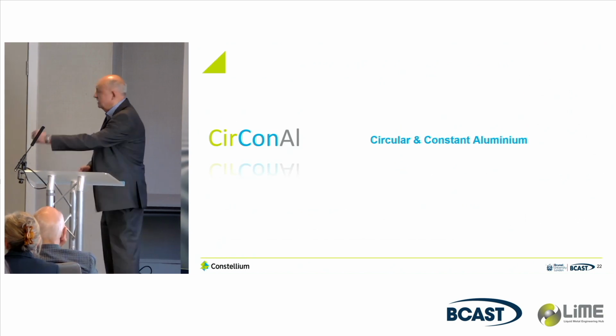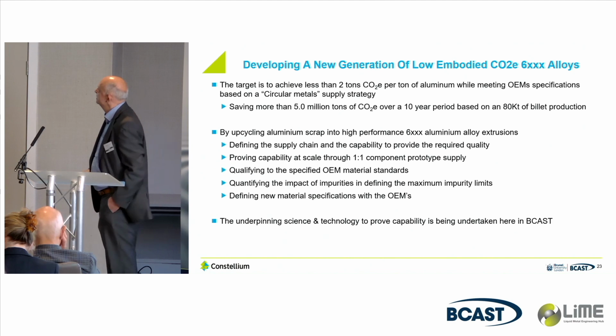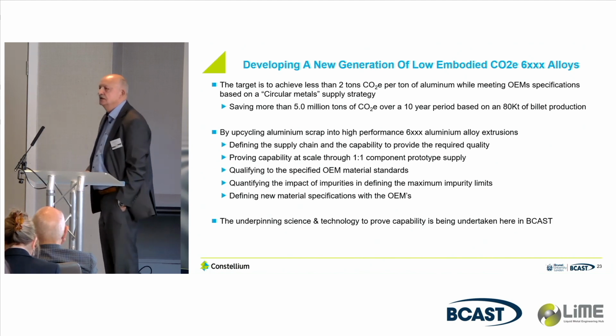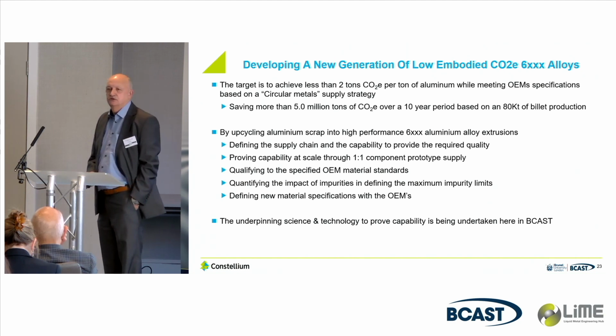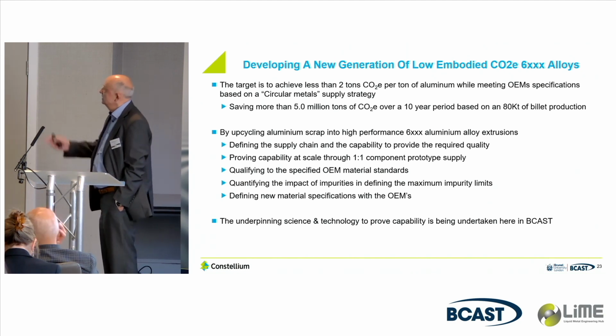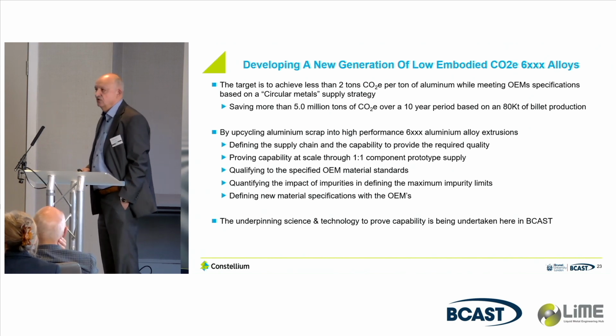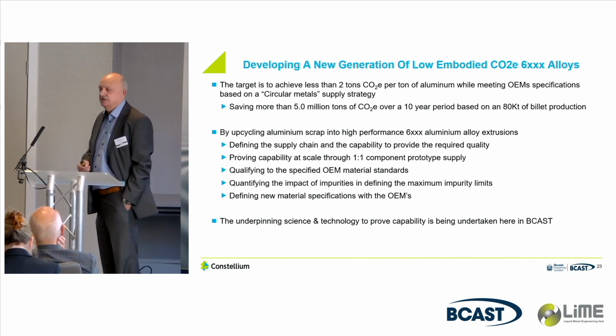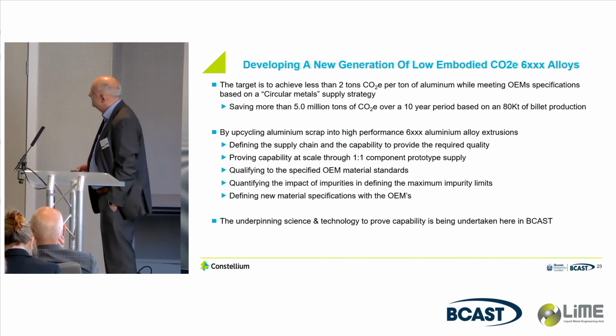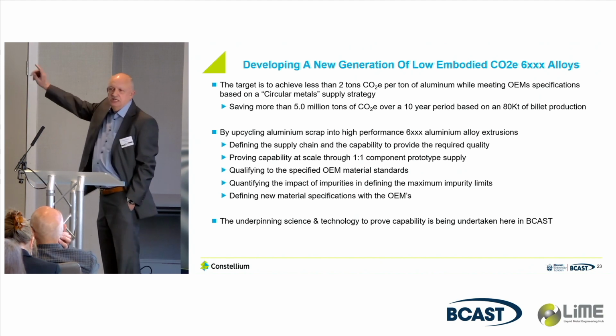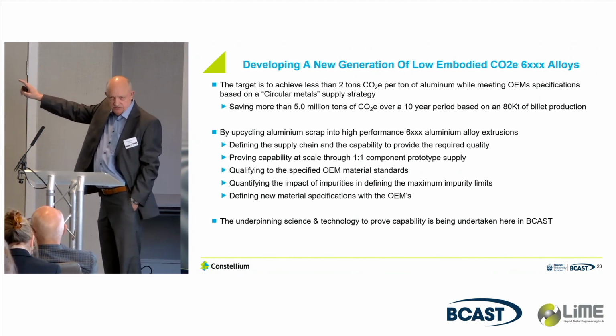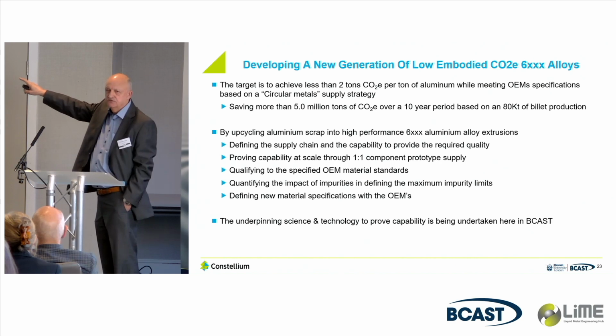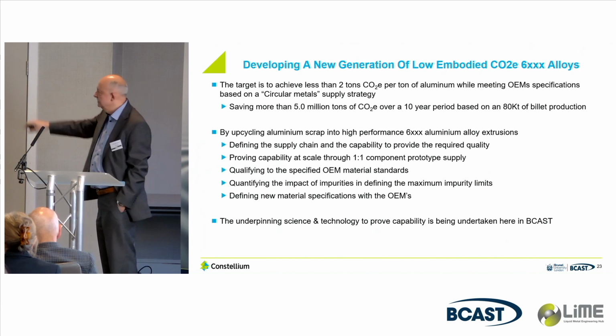So circular and constant aluminium. So what are we trying to do here? So the target is to achieve less than 2 tonnes of CO2 per tonne of aluminium. And just to give you some sort of context of what that means versus the average European number, which is around about 10, over a 10-year period using an 80,000 tonne cast house, that saves 5 million tonnes of CO2. So these are not small numbers.